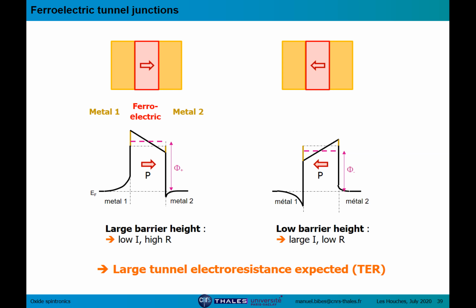This is important because it involves the screening length, screening of the polarization charges from the ferroelectric, and we need metals with two different screening lengths. So what happens when the barrier is made ferroelectric? While you are in the ferroelectric, you have polarization charges that will be screened by electrons in the metals, okay? And so this accumulation or depletion of charges will occur over a finite thickness, the Thomas-Fermi screening length, and it can be typically a few angstroms or a few nanometers depending on the metals. And if the screening is poor, you will have an added potential at the interface between the metal and the barrier, okay? When the screening is good, this potential will be small.